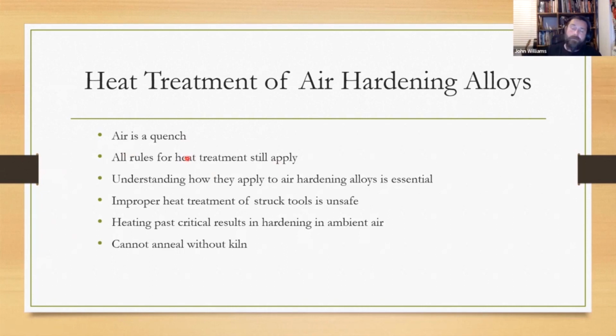You can still anneal it, for instance. But to anneal it, you've got to have the annealing process go over a 24-hour period in an electric kiln where it's coming down, 15 degrees or such and such degrees over every 15 minutes. So you can't do that in a shop setting. And that's really important, because if you're not understanding what's going on, you could make an unsafe tool. You could still have hardness on the struck end. So what that means is, now that we've talked about what's going on, if you heat past critical temperature on an air hardening steel, and air is your quench, then you know that if you get this hot enough, then it will quench. So you can't normalize this or anneal this in a practical way in the shop.